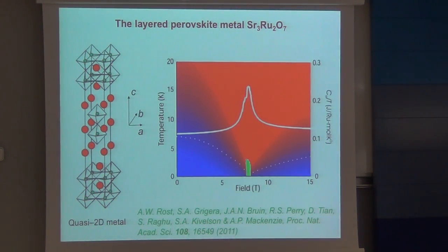And we've done a lot of work on this over the past 10 or 12 years. And what we're able to show is that in some senses it's a canonical quantum critical system. So here there are many things on this diagram. So first of all, look at the color from blue to red. This color coding is a cartoon trying to tell you that when it's blue, the resistivity is going as T squared, so it's the resistivity of a Fermi liquid. When it's red, the resistivity is going linearly in temperature, and this is often seen when you're tuning towards a quantum critical point. When you're sitting above the quantum critical point, for reasons that aren't very well understood, the resistivity is linear in temperature. This is one of the reasons people are interested in quantum criticality in the high TCs.